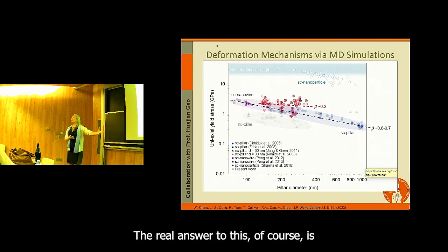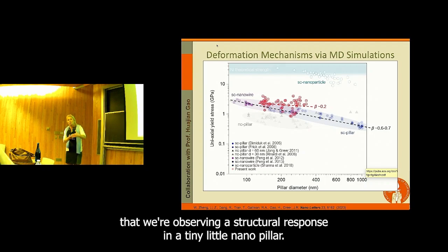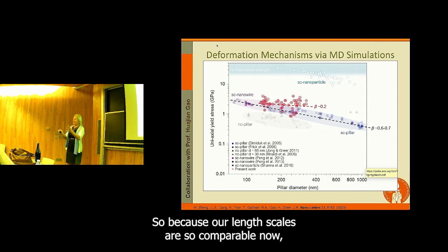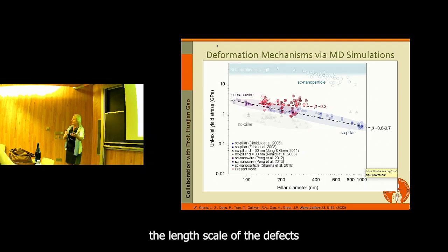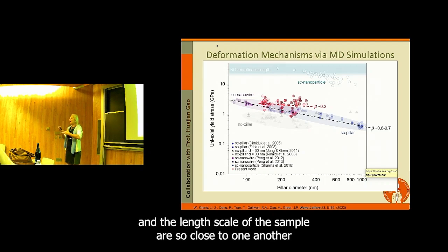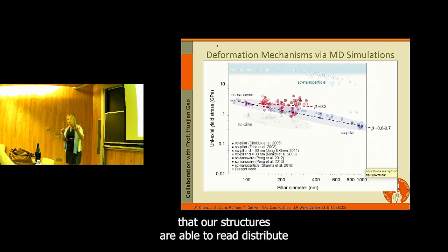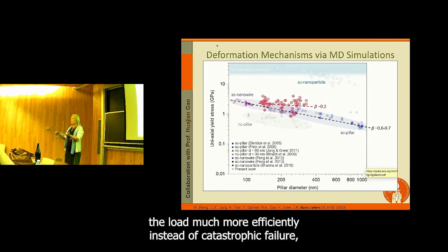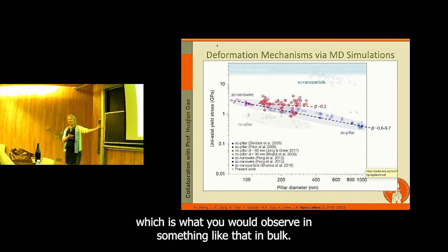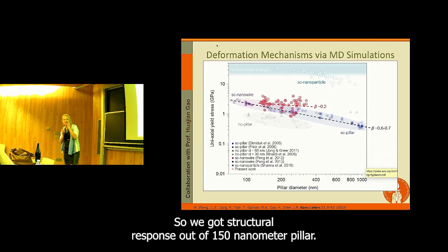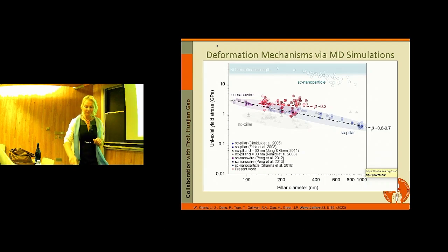The real answer to this, of course, is that we're observing a structural response in a tiny little nanopillar. Because our length scales are so comparable now, the length scale of the defects and the length scale of the sample are so close to one another that our structures are able to redistribute the load much more efficiently instead of catastrophic failure, which is what you would observe in bulk. So we got structural response out of a 150 nanometer pillar.